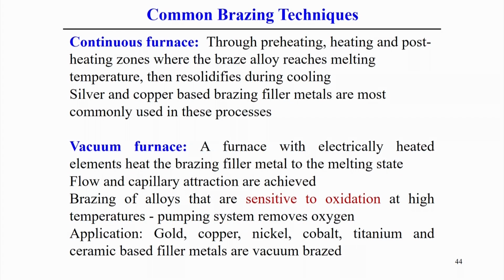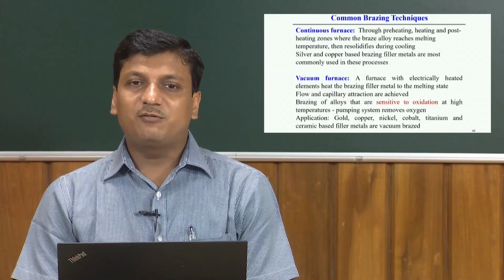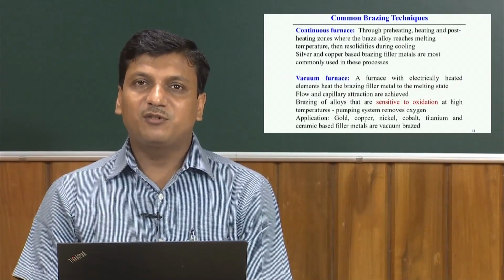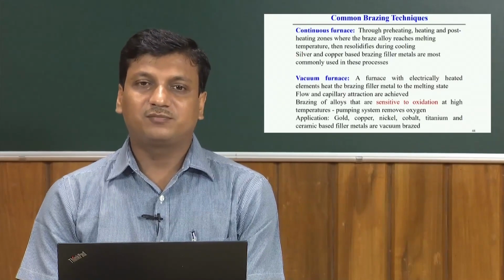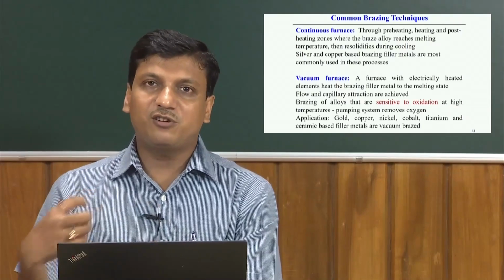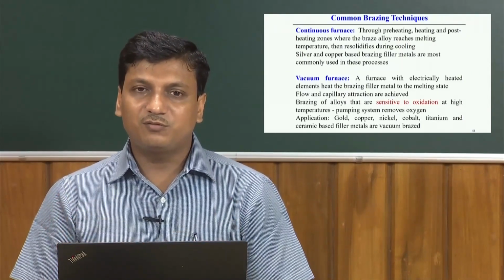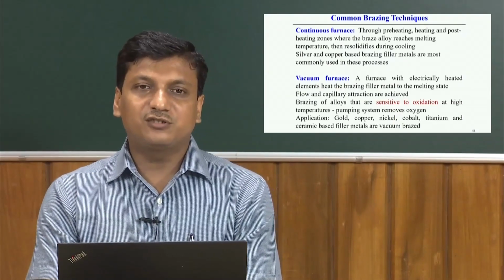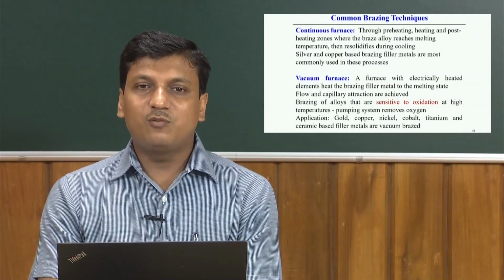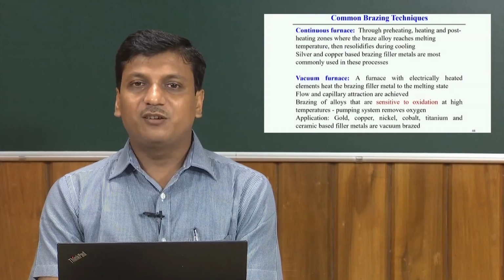Sometimes the vacuum furnace process will be costly as compared to the other brazing techniques, but if there is an application of certain materials which are very sensitive to oxidation, and that oxidation normally increases with temperature, then to avoid the oxidation of the material there is a need for vacuum furnace techniques to successfully assemble the different components. The pumping system removes the oxygen from the zone where the workpiece is kept. Gold, copper, nickel, cobalt, titanium and ceramic based filler materials are generally vacuum brazed.